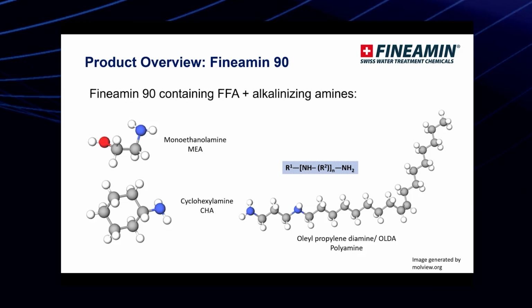as a short form. So in this case, as you can see, the molecular structure of the OLDA is a long chain alkyl carbon chain. If you see here, you have one amino group here and another one here. This is the N: the blue is the nitrogen, red is oxygen, and H is the hydrogen. So there is one amino group here, one nitrogen, and a second nitrogen here. This is what we call the polyamine. It has a certain structure that will attach to the metal surface and give the hydrophobicity effect. It is the long chain alkyl carbon chain that will have the hydrophobicity effects.